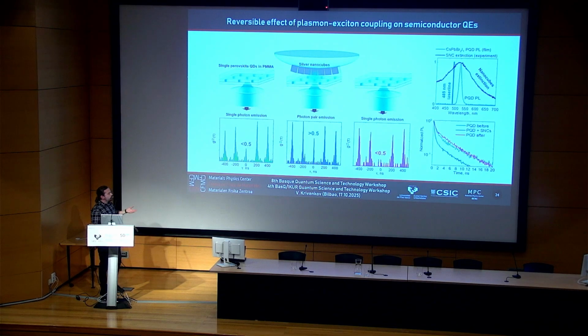So we're wondering if we could control it on demand or deterministically. And yes, we can do that. We can look at the same quantum dot before the interaction, during interaction, and after interaction with the plasmonic particles. And yes, we can switch the emission from the single photon emission statistics to the emission of photon pairs and back to the single photon emission with the changing of the emission lifetime.